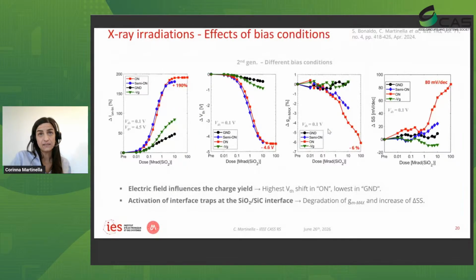There is a dependency on the bias conditions, particularly on the electric field that is applied at the gate during the exposure. So the charge yield changes with the electric field. When we study this effect, we always look into some specific figures of merit to see how the MOSFET is performing. So we look at the on-state current, the delta of the threshold voltage shift between the different points, the transconductance, and the subthreshold swing.